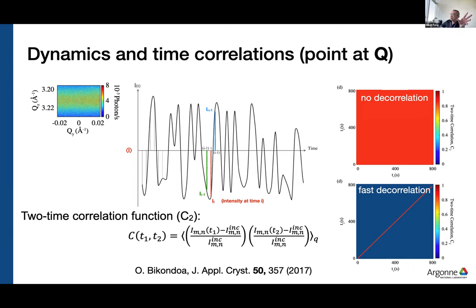you could look at this CCD image of your Bragg peak or whatever you're looking at as a function of time, and you can essentially look at the average, which is the horizontal line, okay? That's not really changing with time. But if you look at the speckle, that is fluctuating with time. And so if you took your same material, took it down to very low temperature, tried to do a two-time correlation function, you may not see anything. You would see this red square because there's no decorrelation.